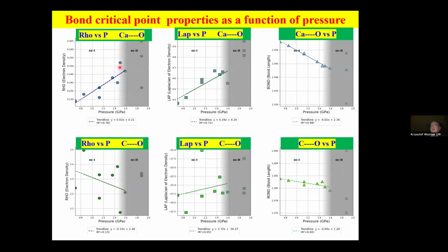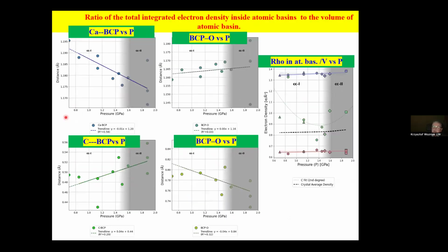And we can really get far more details. For example, how electron density at the bond critical point is changing when we increase pressure. But in the case of, say, contacts to carbon atom, we are not getting nice relations, but only very broad scatter of data points.